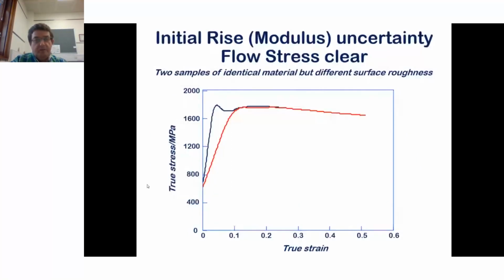If you've got two samples of an identical material, but you put different surface roughnesses on it, so the way the beginning of the stress rise is affected by that surface roughness, you will get those two different angles of stress strain at the beginning. But the flow stress, when the material is moving sideways, as you see, the top of those lines match quite well. So Hopkinson bar, a lot of discussion, but flow stresses measures really well, really accurately.